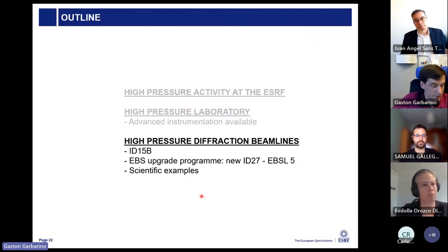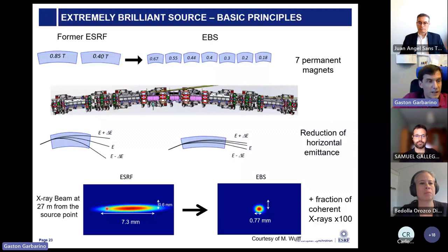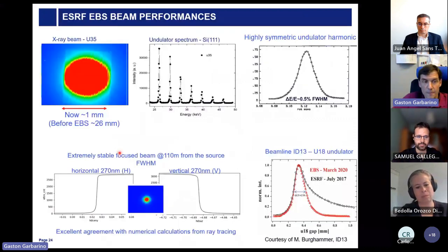So I will just present some examples in the time that is remaining: ID15B and the new ID27. This is just to show you how the beam improved. At the beginning, on the old ESRF, we had a beam that was roughly 7 millimeters large, and now at the source it is of the order of 0.7, so 10 times smaller. And this can be transferred immediately into much better focusing of your X-ray beam. So nowadays at ID27, one of the high pressure diffraction beamlines, the beam is below 300 nanometers.